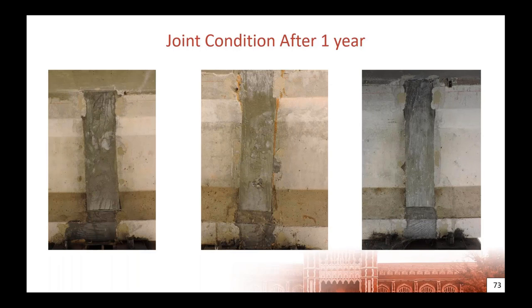It was, in fact, just superficial damage on the surface. There wasn't any indication that damage extended any farther. And then the other two joints appeared to be performing just fine. There's no apparent damage. And in the left picture, you see where some of the UHPC reached into the damage caused by the demolition, and it still maintained there, even in a thin section; it was not pulled off. Next slide.